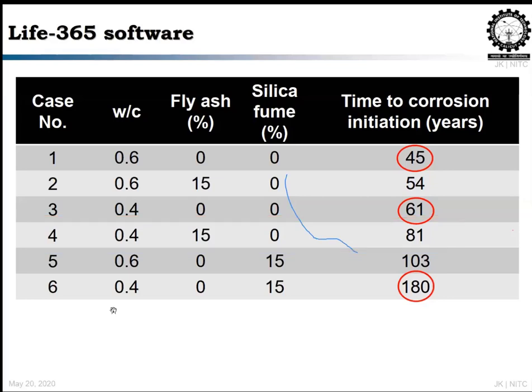If you use silica fume instead of fly ash, at 15%, which is very high, with different water cement ratios of 0.6 and 0.4, it is 103 and 180 years, which is nowhere comparable with your 45 years. It means you can double or prolong your service life. That is for sure. So don't think that the use of SCM is to save money or use waste. It is really there to support you in enhancing durability.